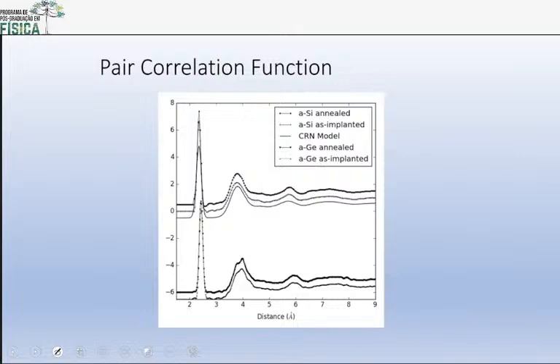We also measured amorphous silicon that's been annealed and germanium that's been annealed. What does that mean? So if you produce this amorphous silicon and you heat it up just a bit, heat can be given off. And that means when heat gets given off by the sample, it's going to a lower energy state, right? And so then comes this idea, and this is a whole other field of defects in amorphous materials. What does it mean to have an amorphous material give off heat and become maybe a better amorphous material? And how did it become better? How did it go to a lower energy state?